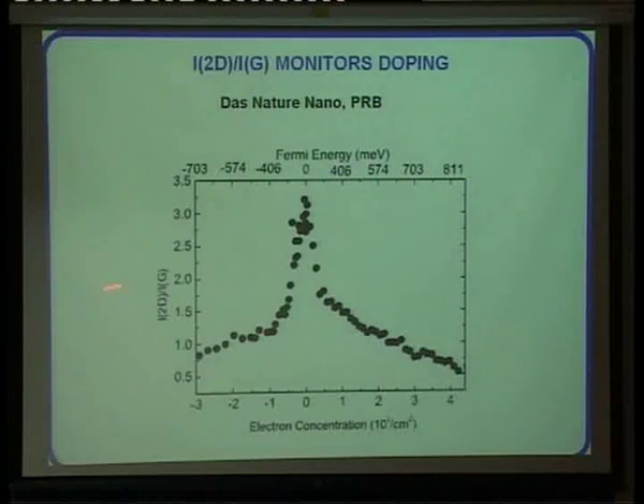And that was explained, as I showed before, by the fact that you change the electron-electron interaction by changing the doping level, and so the intensity of the 2D peak is changing with respect to that of the G peak. There is however, even with polymer electrolyte, as good as it is, you cannot really get 1 to 1.5 eV of doping, because if you do try, what happens is that you damage the sample. There are some interactions between the polymer and the graphene.